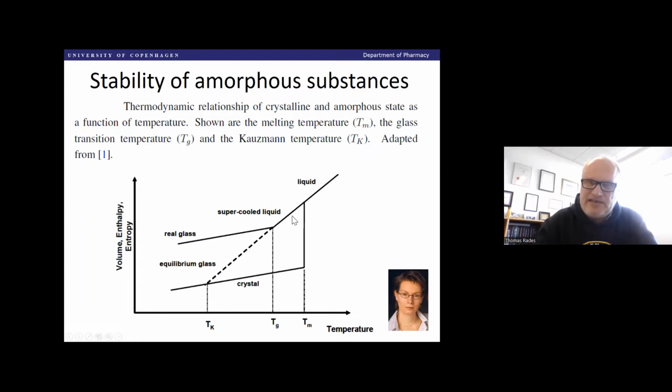So here we have a material that is out of equilibrium with the crystalline phase, so it's a high energy form, but it still is able to follow the cooling rate. So the path that we are following from the melt is still followed. But at some point in time, molecular mobility becomes so slow that the cooling rate will be too fast for the material, at any given temperature, to get into equilibrium with that particular temperature. In other words, we are falling out of equilibrium with the cooling rate, and here we get a change in the slope of our thermodynamic properties,